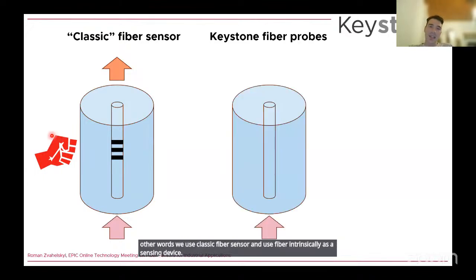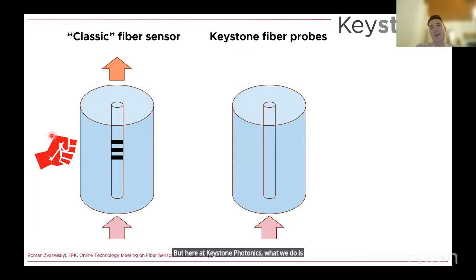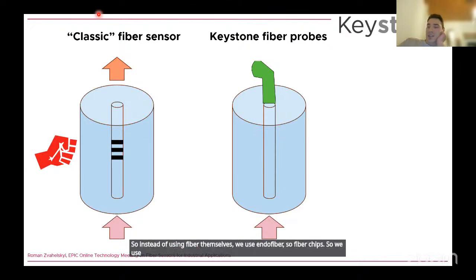I would like to start with the definition of a classic fiber sensor. Here we detect reflection or transmission shift due to changes in temperature or strain. This is represented by a fist hitting a fiber here. Typically we use fiber Bragg gratings. In other words, we use a classic fiber sensor and use the fiber intrinsically as a sensing device. But here at Keystone Photonics, we produce fiber probes. So instead of using the fiber itself, we use the end of the fiber, the fiber tips. We use the additive technology of 3D laser printing.